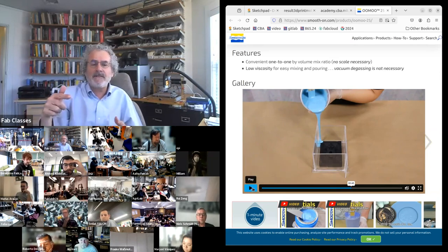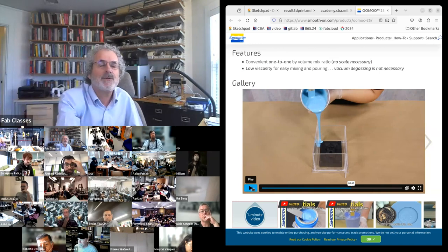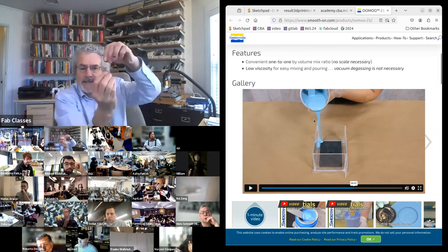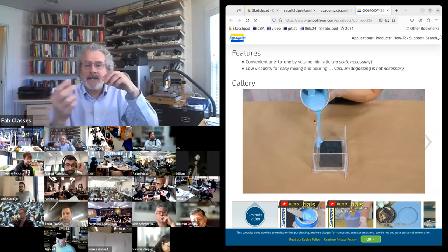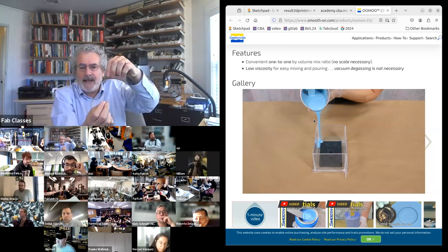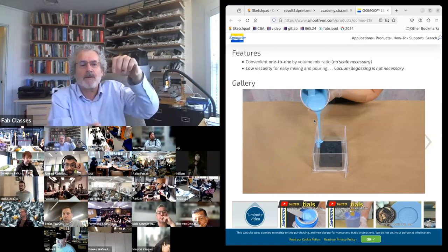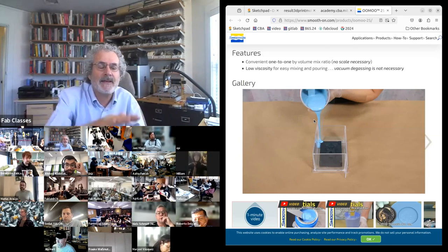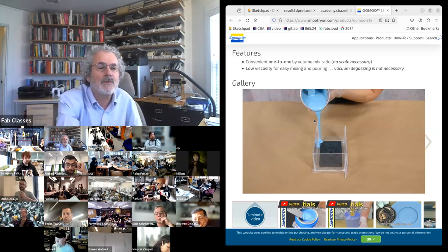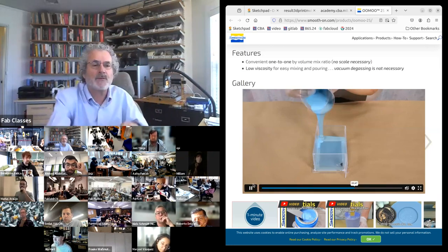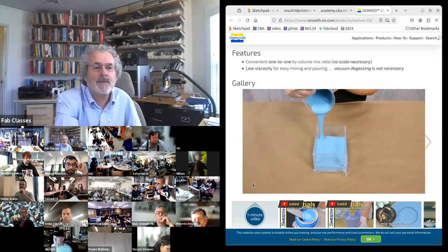The pouring is being done very carefully. If you dump it in, you trap air. And then you'll see it's being poured in a skinny bead. The skinny bead is helping to prevent air getting in the mold because if there's bubbles, they'll pop on the way down. And then it's spreading slowly through the mold so it has time to make its way in. Slowly spreading.